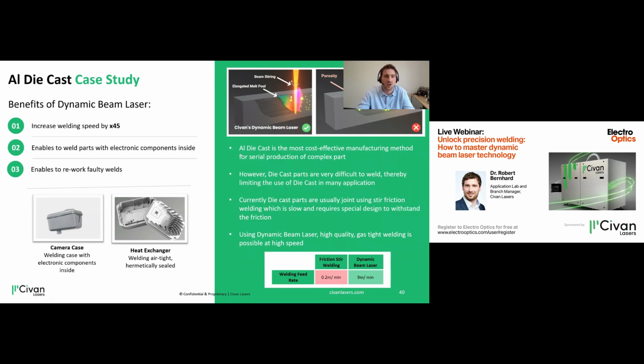And laser welding also has many advantages. One of them is that we can weld the parts with the components inside because we have such low energy input and no vibrations, and we are able to do the rework of welds with our laser. So this finally means we are able to do the welding of die cast parts with very low porosity.